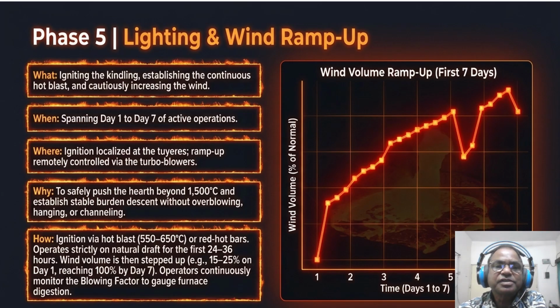Our operators are continuously monitoring the blowing factor, the relationship between the blast pressure and the wind rate, to gauge how well the furnace is digesting the raw material. We are pushing the hearth beyond 1500 degrees centigrade, but we must do so cautiously to avoid channeling, where gas bypasses the burden, or hanging, where the material stops descending.